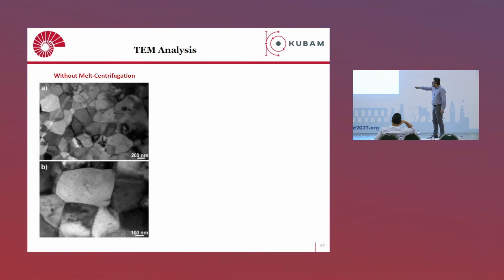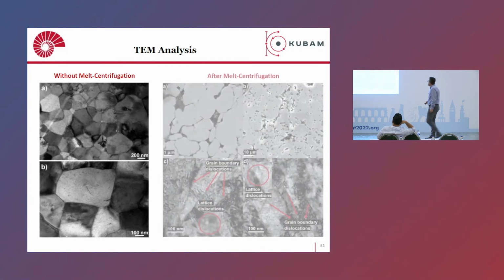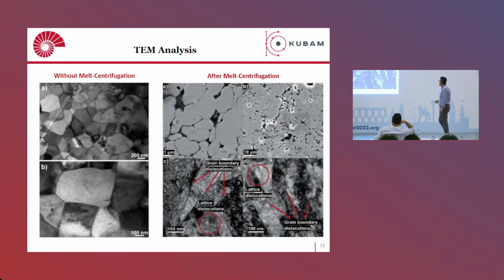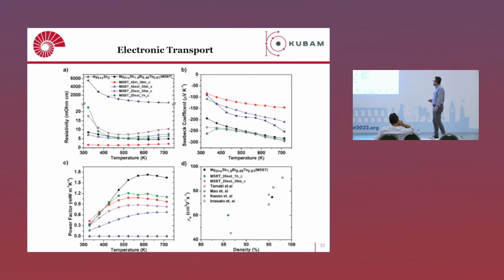So this is the microstructure with TEM without melt centrifugation. You can see a very condensed, highly condensed, regular microstructure, let's say. And you can see that the average grain size is a couple of hundred nanometers. What happens if we apply this melt centrifugation? We create large pores, as you can see here, but at the same time small pores, which means microscale pores or nanoscale pores. At the same time, you can see that we create these ordered grain boundaries. They are nicely ordered, right? It is completely different from these grain boundaries. Plus, we show that we also have some lattice dislocations within these grains. And we hope that this substantially reduces the thermal conductivity.